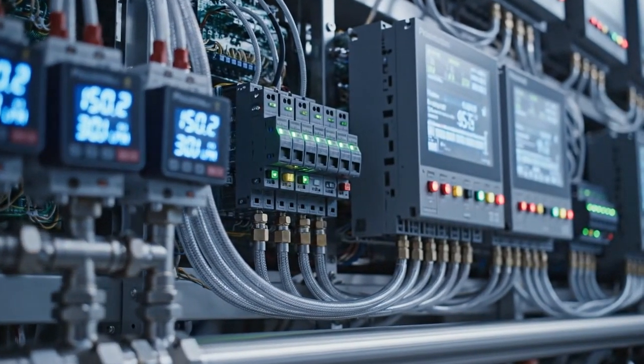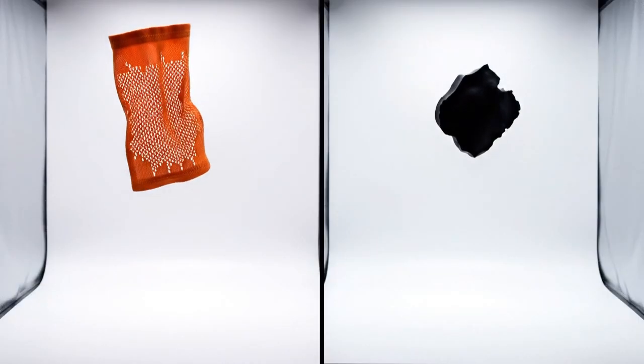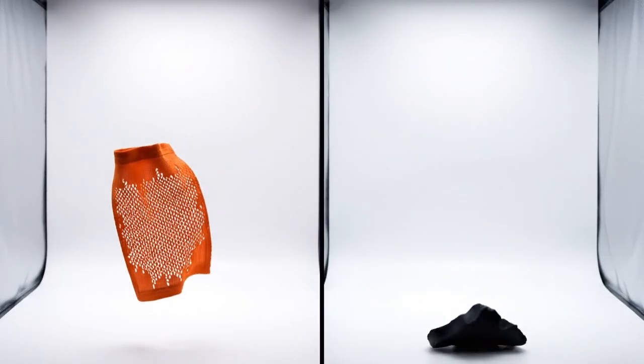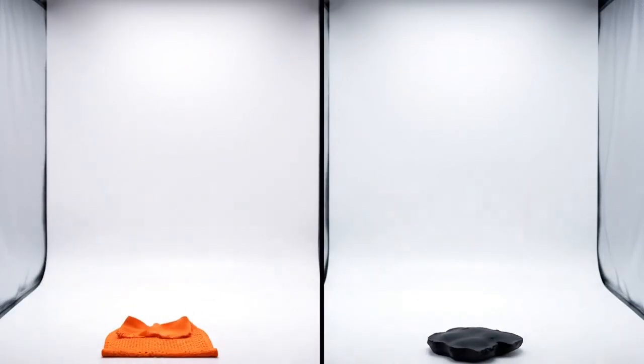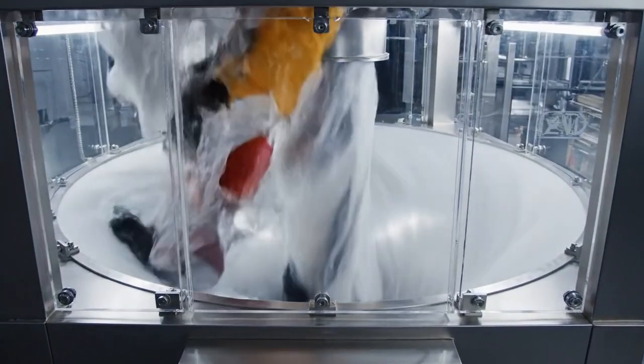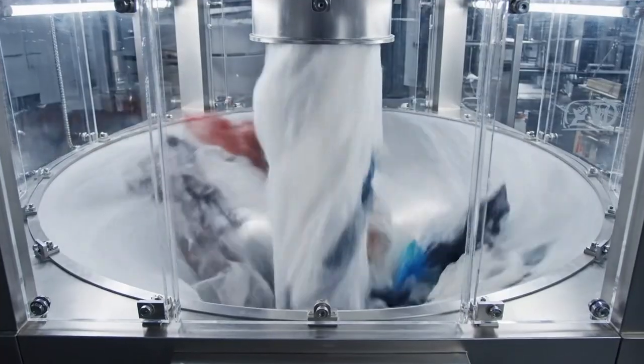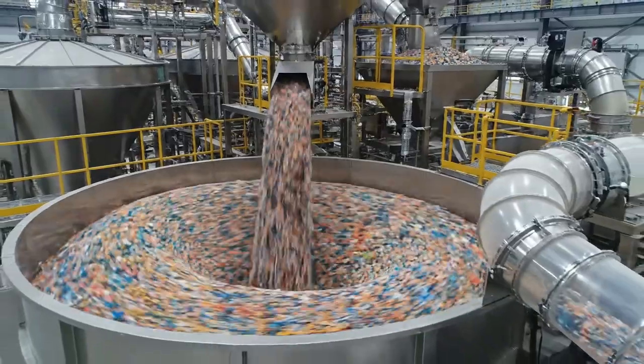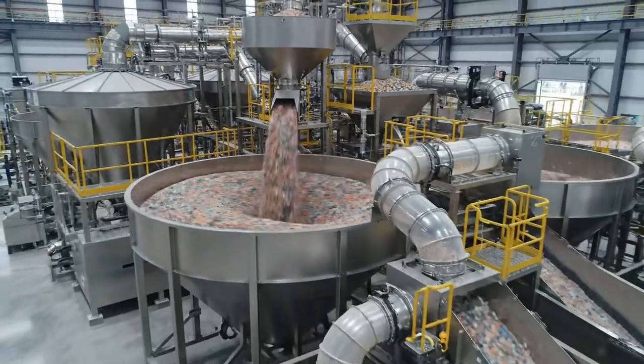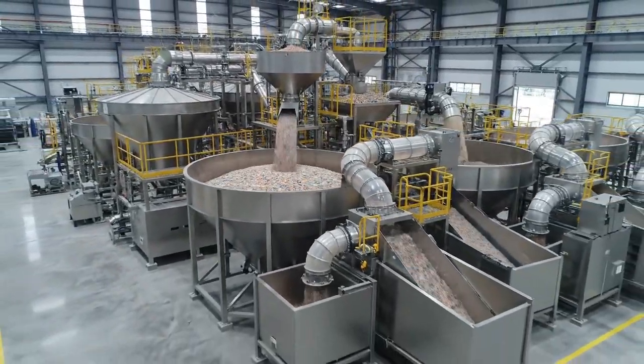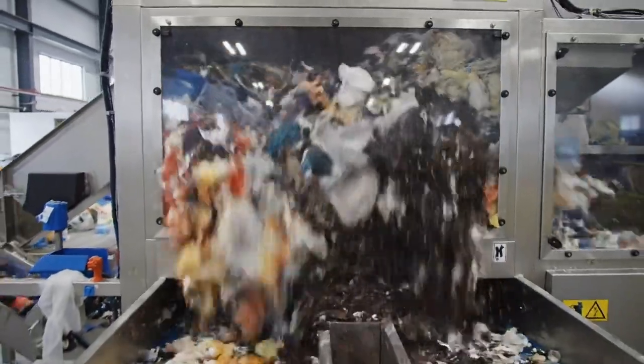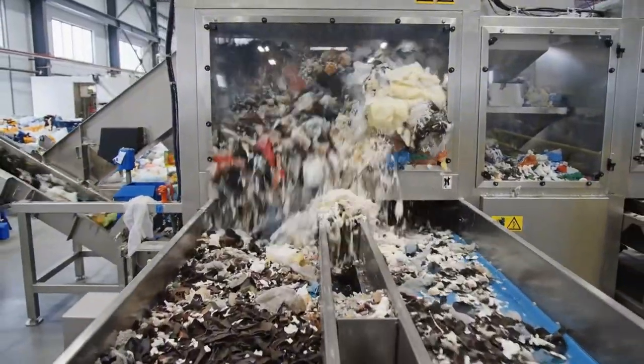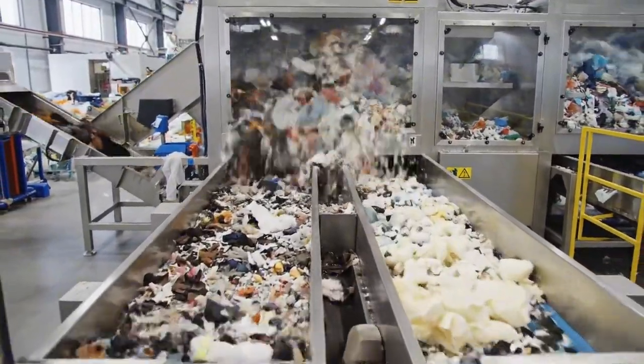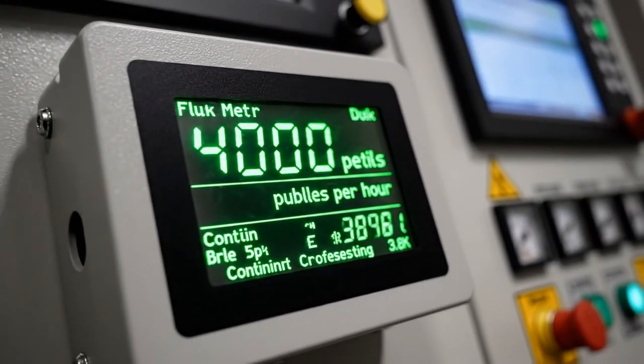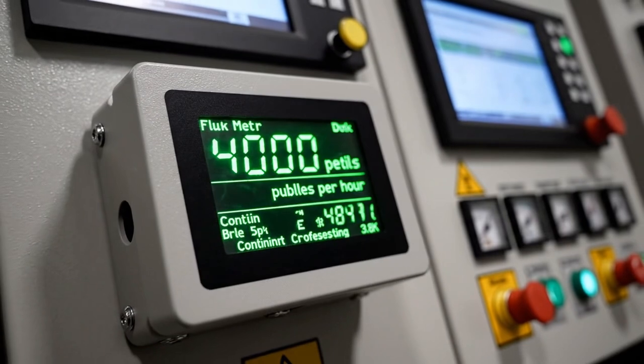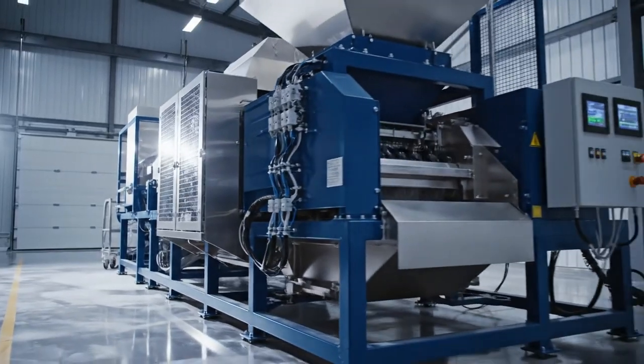The air speed is calibrated precisely, adjusted in real time by pressure sensors and flow meters that communicate with programmable logic controllers. Different materials have different aerodynamic properties. A piece of lightweight fly-knit fabric will be carried at lower air velocities than a dense rubber outsole fragment. The system exploits these differences, creating the first crude separation. Lighter materials are deposited in one cyclone separator, while heavier materials continue through the duct to a secondary collection point. This is pneumatic classification, an elegant application of fluid dynamics to materials recovery. And it happens continuously at a throughput rate of approximately 4,000 pounds per hour.